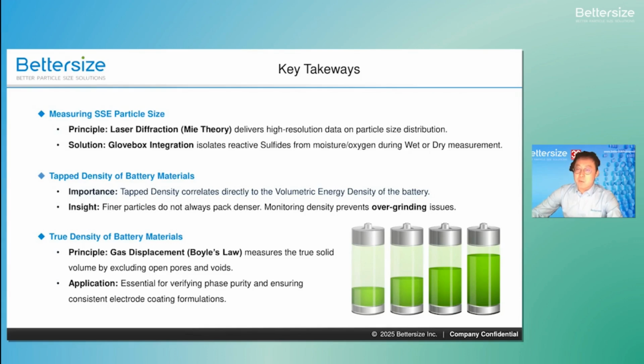First, for particle size, we rely on laser diffraction and Mie Theory for the highest resolution data. But for sulfides, the physics is useless without safety. That is why glove box integration with the Bettersize 2600 is essential. It ensures you measure the actual particle, not a hydrolyzed degradation product.